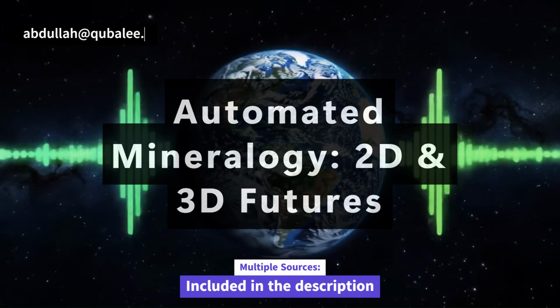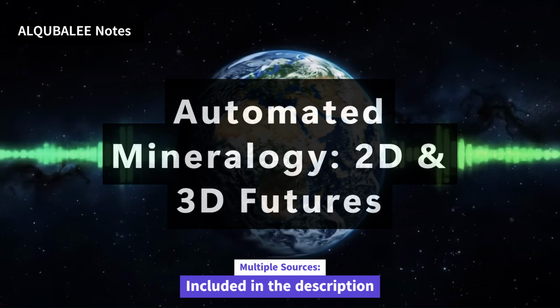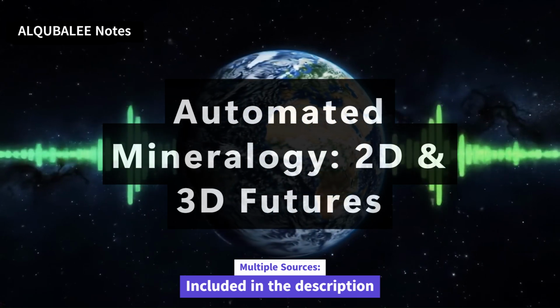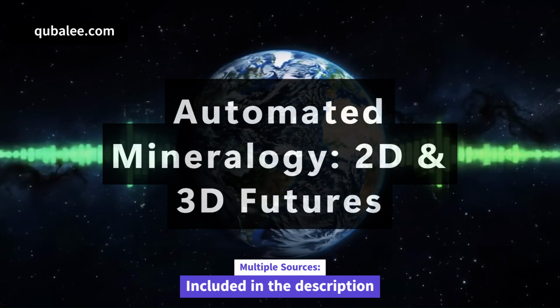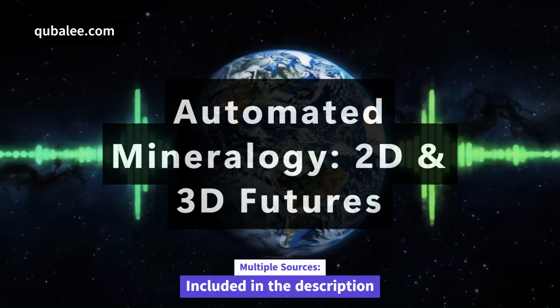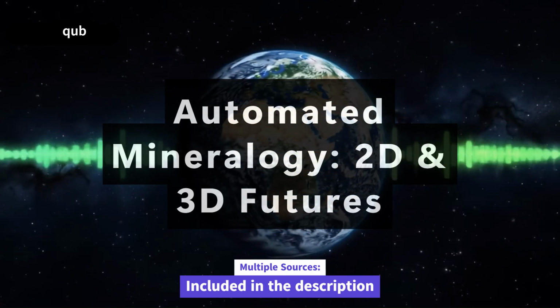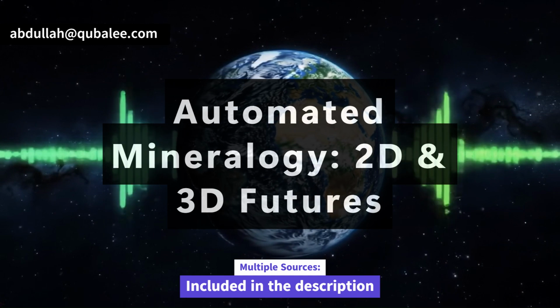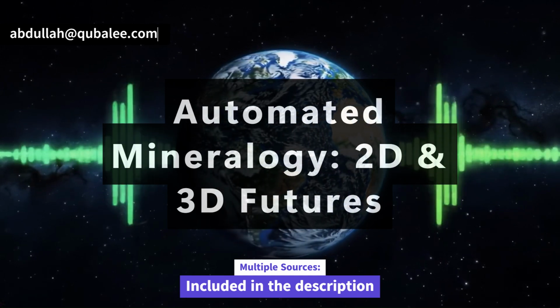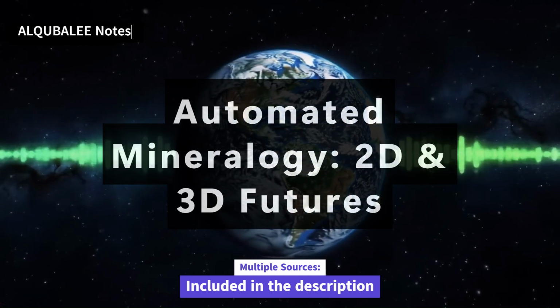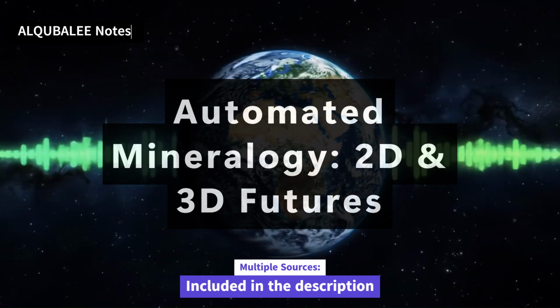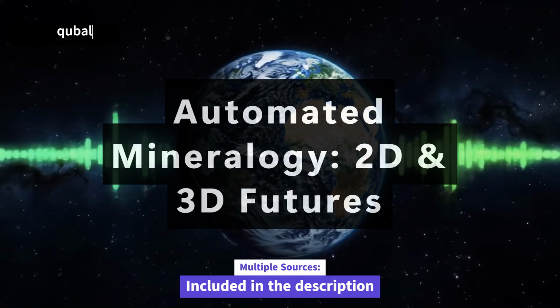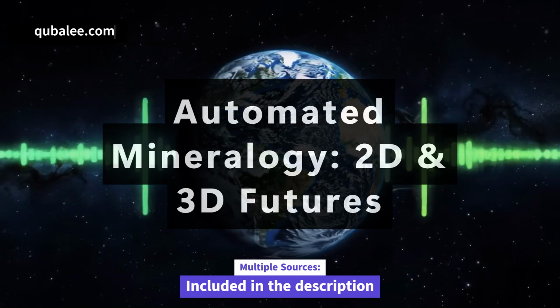Absolutely. Understanding exactly how these critical elements are hosted in the rock, which minerals contain them, how big the grains are, who their neighbors are, that's vital for figuring out if you can actually recover them economically. Take tellurium. Tellurium, right? Often a byproduct, often from copper processing. In one deposit they studied, automated mineralogy identified something like 17 different telluride minerals. Just an incredible diversity. So 17, just for tellurium.